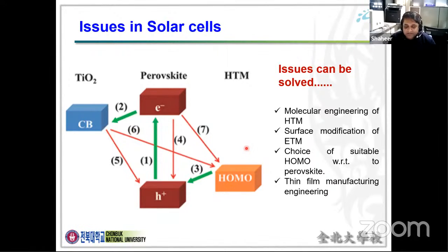So in the typical perovskite solar cells, there are some issues. In the normal case, this green line is like, if our cell has no issue, it means there are no recombination sites or any trapping sites in the cell. So the normal current flow goes like this, but the red color is indicating the recombination sites. These kinds of issues we can solve by some molecular engineering, surface modification of the hole transporting materials, and also choosing suitable HOMO-type material. Maybe I will show you the 2D layered materials, which are very famous nowadays, and some thin film manufacturing engineering we can also adopt to solve these kinds of issues.